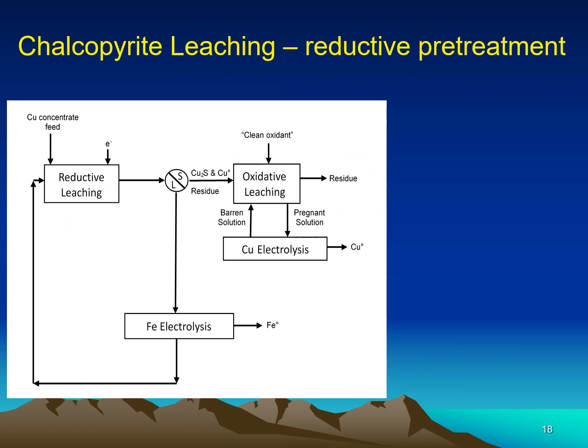The chalcopyrite leaching process with a reductive pretreatment begins with the feeding of the copper concentrate to the reductive leaching or pretreatment phase, where the ferrous ion is liberated and the solution, the pregnant reducing solution, is sent to iron electrolysis.